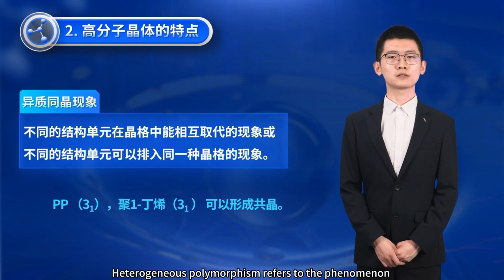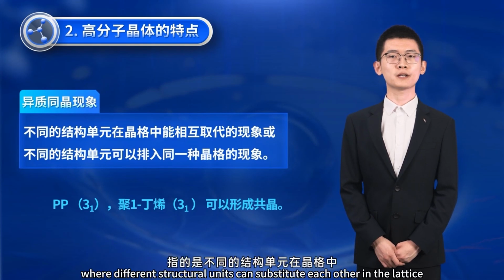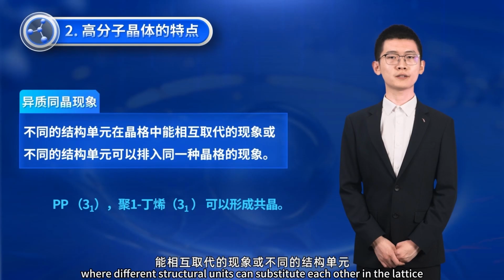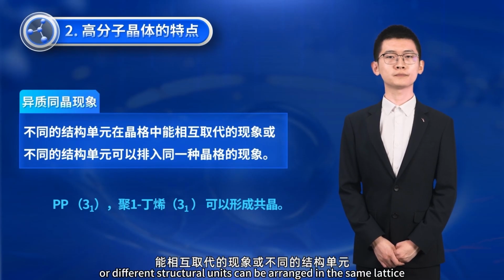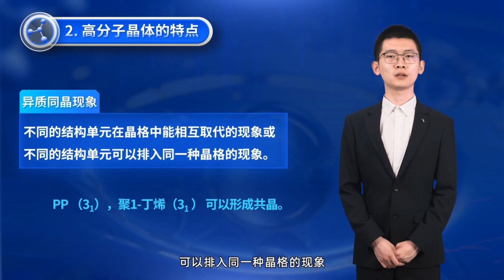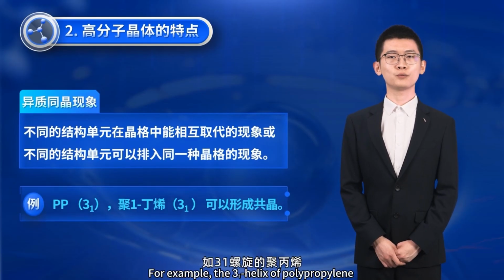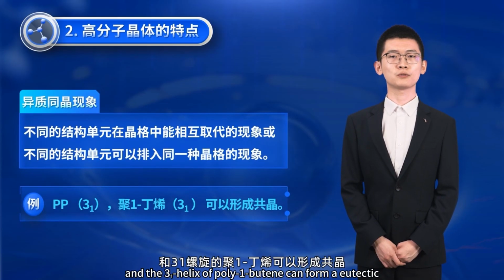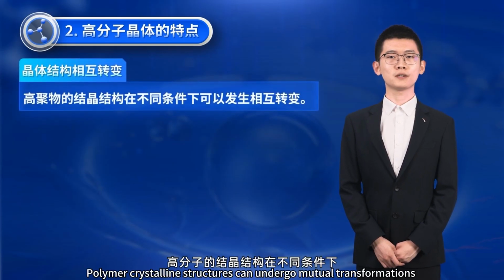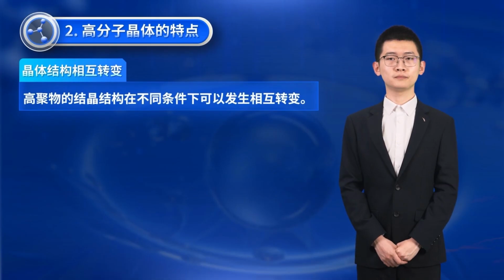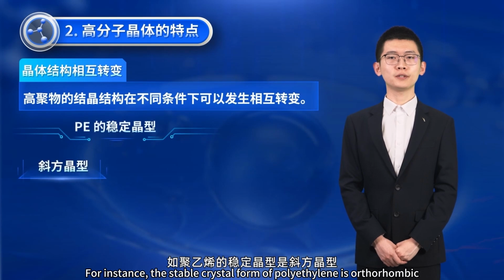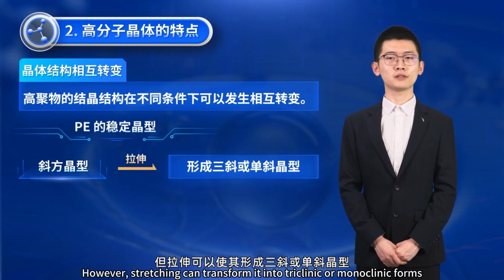Heterogeneous polymorphism refers to the phenomenon where different structural units can substitute each other in the lattice, or different structural units can be arranged in the same lattice. For example, the 3,1 helix of polypropylene and the 3,1 helix of poly-1-butene can form a eutectic. Polymer crystalline structures can undergo mutual transformations under different conditions. For instance, the stable crystal form of polyethylene is orthorhombic. However, stretching can transform it into triclinic or monoclinic forms.